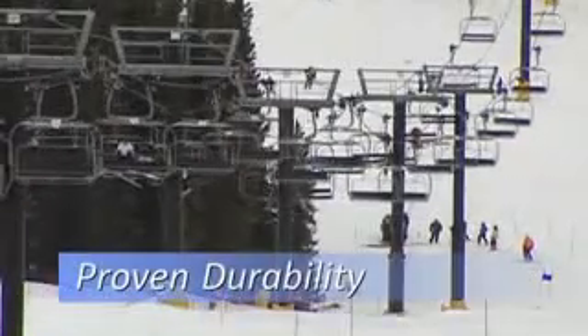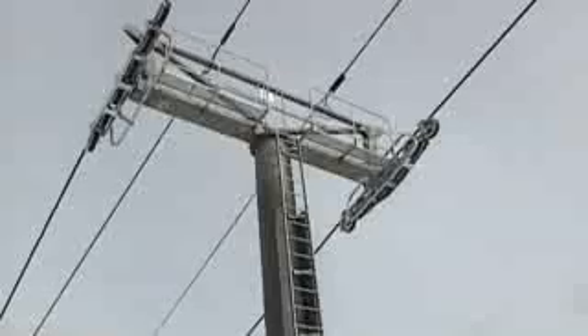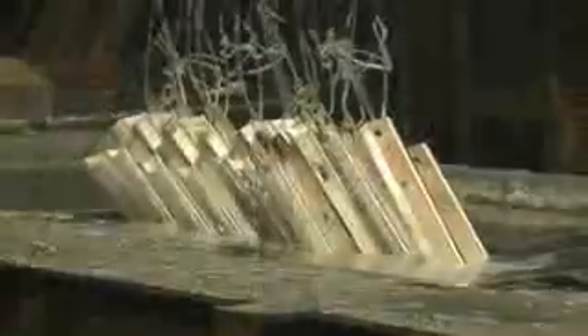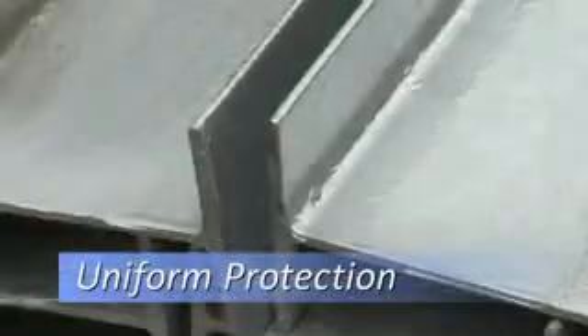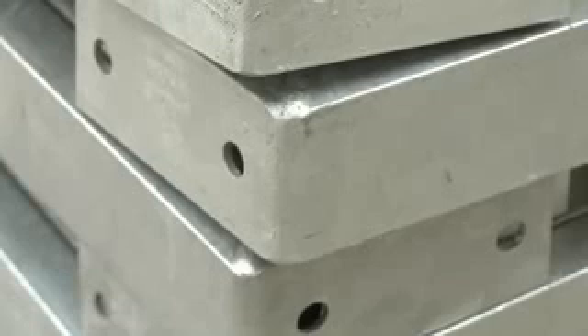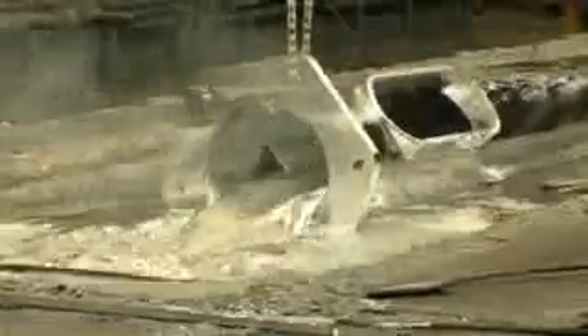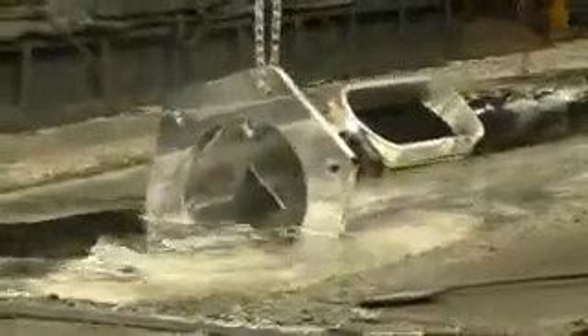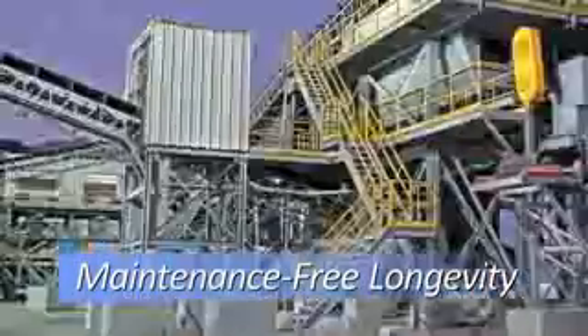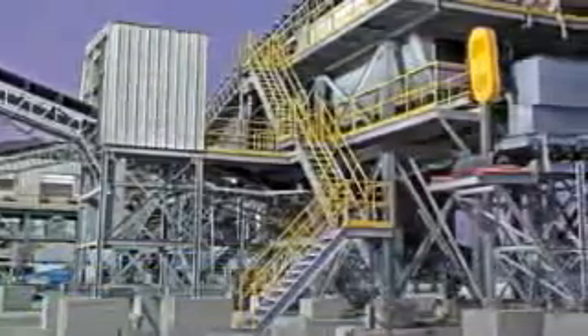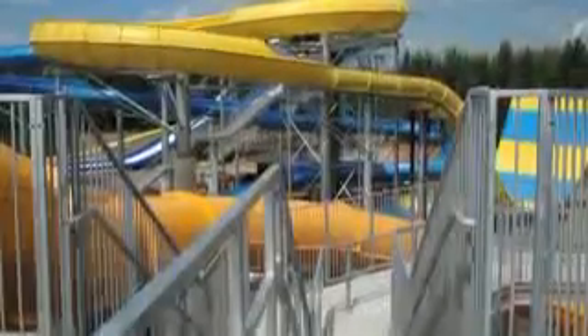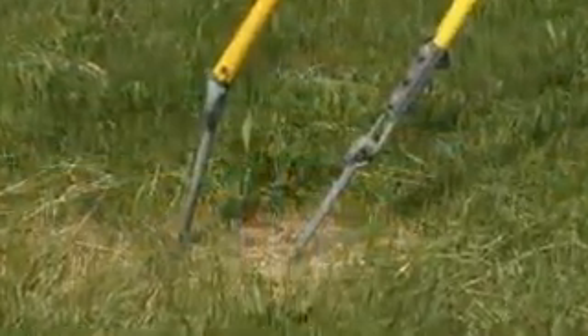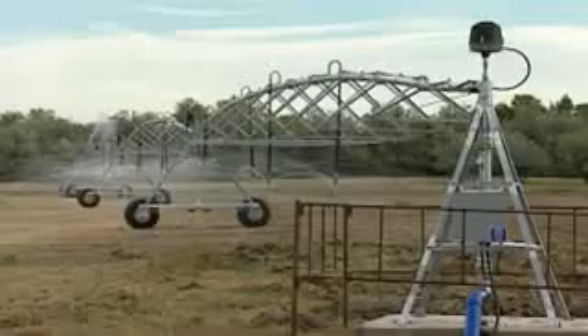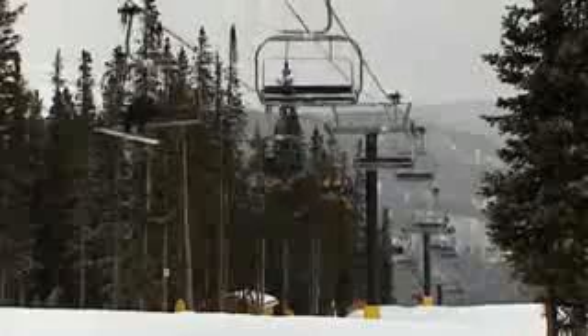Galvanized steel products deliver proven durability, even in harsh conditions. The intermetallic layers formed in the galvanizing kettle make the coating harder than the base steel. This provides unparalleled abrasion resistance. Galvanizing also provides uniform protection. The zinc coating grows perpendicular to the steel, so corners and edges have the same thickness as flat surfaces. The immersion process also ensures hollow and tubular structures are evenly coated and protected inside and out. Because of its maintenance-free longevity, hot-dip galvanized steel is utilized in some of the harshest environments. Commonly used on structures exposed to the atmosphere, galvanized steel can provide over 70 years of maintenance-free corrosion protection. Hot-dip galvanizing is commonly used to protect steel embedded in soil and concrete or submerged in water. Galvanized steel has a proven record of longevity in all of these environments.